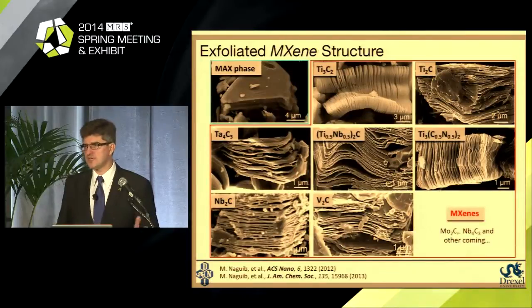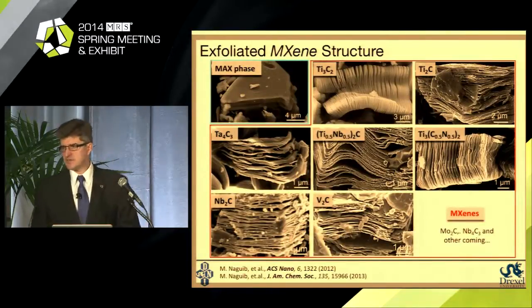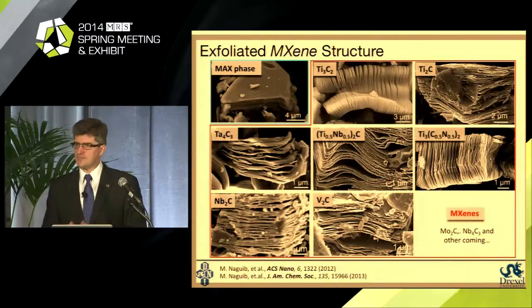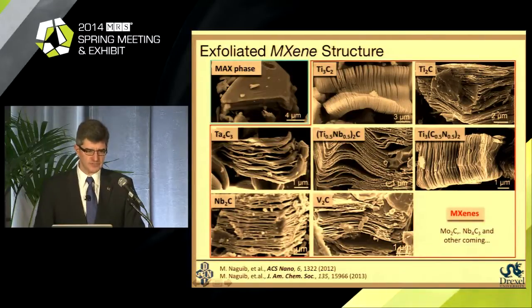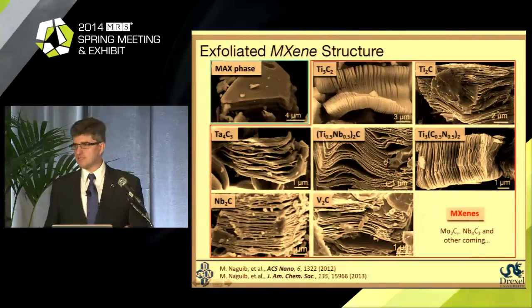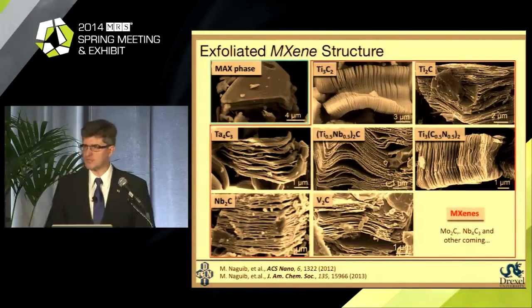And what is important, within less than 3 years, we were able to show that all 3 types of MAX phases, 211, 312, or 413, can be transformed into MXene two-dimensional carbide. So the representative, all 3 of them. We can obtain solid solution on the M side. We can obtain solid solution on the X side. So it basically means that pretty much any MAX phase can be transformed into two-dimensional carbide or carbonitride. We still have to synthesize nitrides, although they have been predicted by DFT calculations by a large number of groups to be stable as well, still somewhat less stable than carbides.